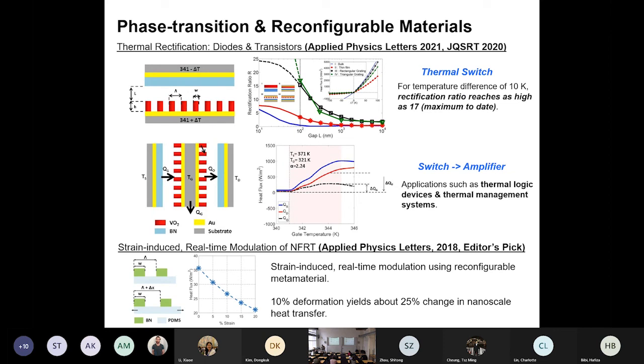Okay, so 10% deformation could yield up to 25% change in the heat transfer. So let's say here the 10% strain, it could reduce the heat flux from 36 down to 27. So more than 25% reduction. So you might ask, 10% deformation is too large, but clearly no. It's for nanoscale. So if we're able to make a pattern, such as grating structure, with a period of only 10 nanometers, then 10% deformation is only 1 nanometer. So 1 nanometer deformation could yield 25% change in near-field thermal radiation. So this concept can be used to design a highly sensitive optical thermal sensor.